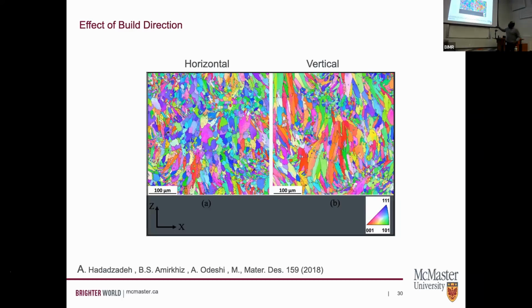So here is the first example. This was from an EBSD map from some colleagues. And what you see is more or less a very uniform microstructure. They're all kind of equiaxed. Here, you see a very heterogeneous microstructure. Some are very columnar, lenticular, and then you see some of these equiaxed regions.